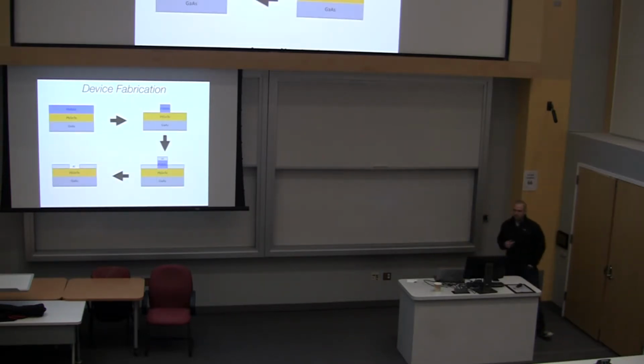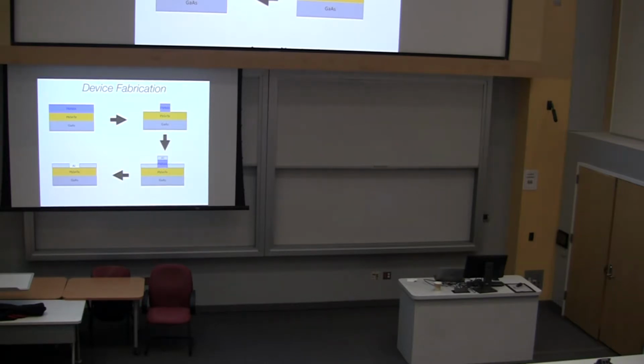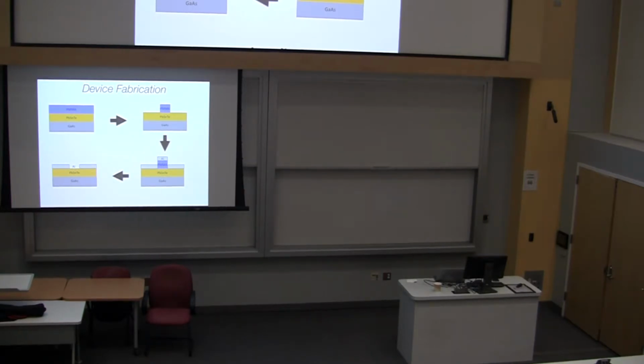So for our junctions, how do we actually make them? We spin the polymer. You guys probably saw a little of this at the practical in the last few days. We spin polymer on top of a topological crystalline insulator, shown here as lead tin telluride. We then expose these regions here and here and develop away the polymer. And then we put this in a sputter deposition chamber, and we sputter a little bit of Ti, about 3 nanometers of Ti as a sticking layer.